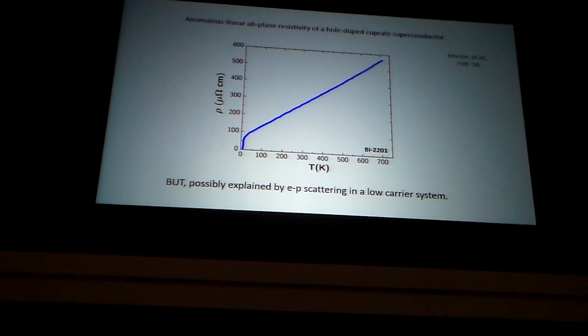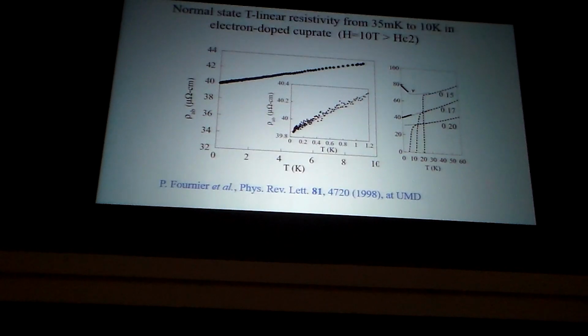So that is certainly a possible explanation for this in this material. However, we did an experiment here on an electron-doped cuprate. Fournier was intimately involved in that experiment. In the normal state of this particular cuprate, we found that this linear in T behavior persisted down to 35 millikelvin. So that definitely cannot be explained by electron-phonon interaction.